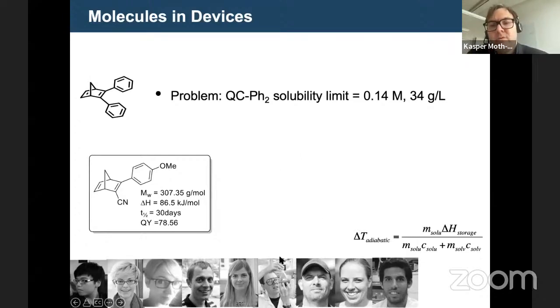And if you look at this formula here, it has the energy storage of the molecule and the mass of the molecule, and then you can calculate how much you can heat up the solution when you trigger the heat release. And that is depending on the mass of the solvent and the heat capacity of the solvent, and the mass of the molecule and the heat capacity of the molecule. So then it becomes clear that it's important to have a lot of molecule and not too much solvent.